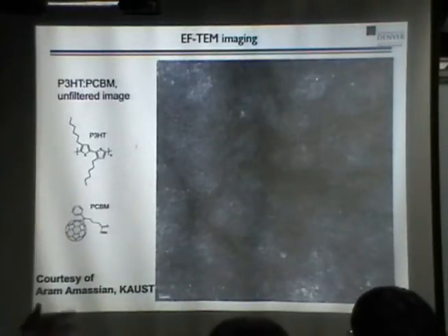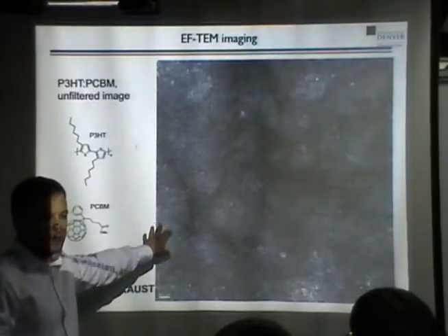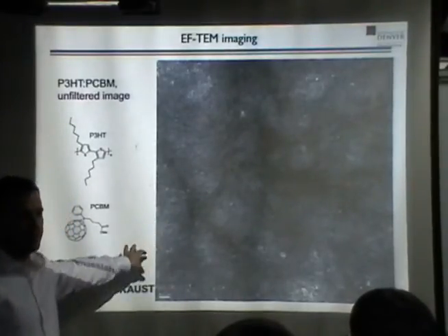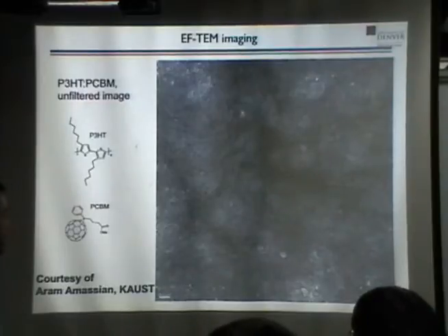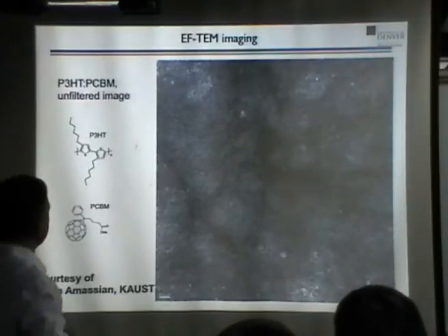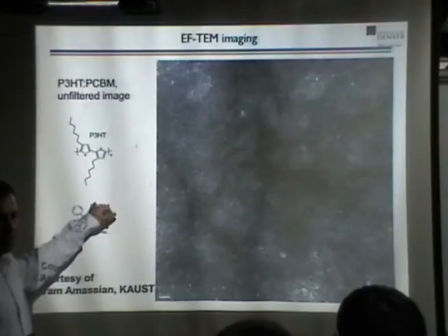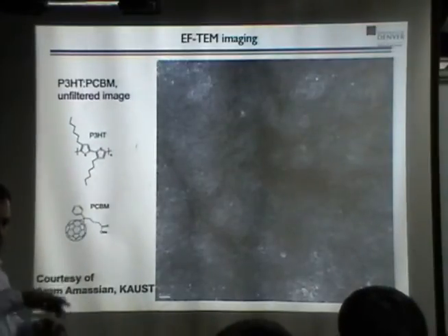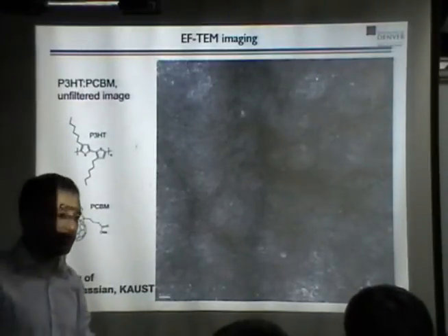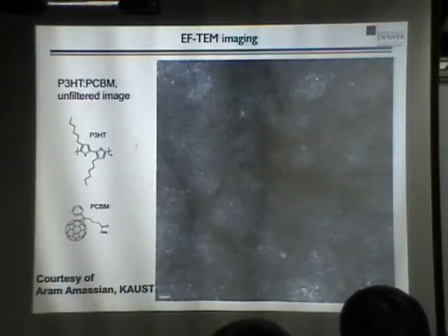So it has different order at different length scales. That's been determined by some more recent TEM data by Julia Shu, my collaborator, where they have even better resolution and can look at individual fibers. It's very analogous to a liquid crystal structure at that point. It just does not exhibit the same differential calorimetry that you would see in a liquid crystal in terms of different phases and transitions. But all the driving forces are the same.